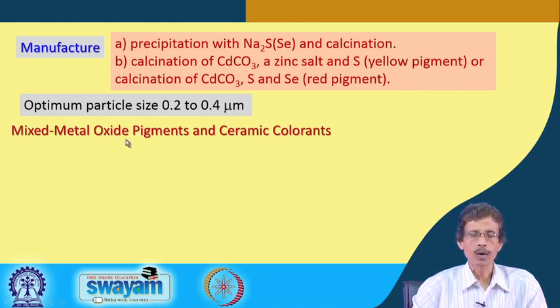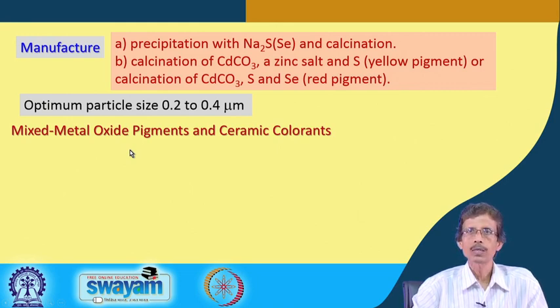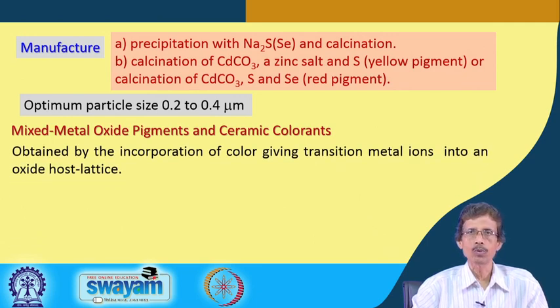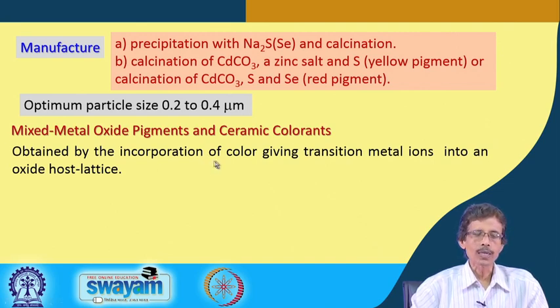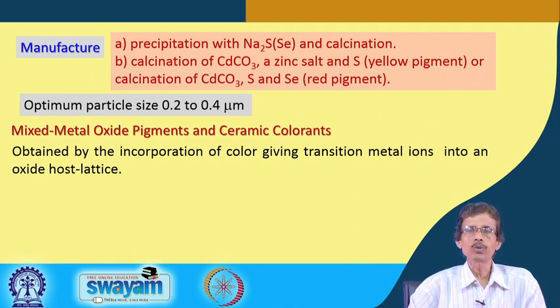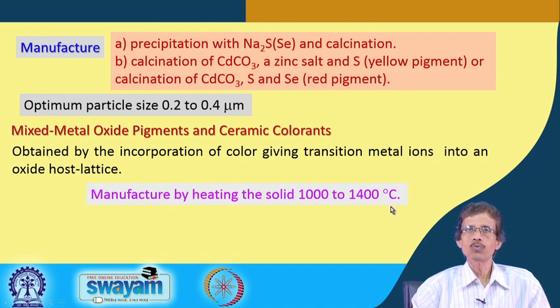Mixed metal oxide pigments are useful for ceramic applications. These are spinels — mixed oxides with high thermal stability compared to individual oxides. Colored transition metal ions are incorporated into colorless oxide host lattices such as alumina or magnesium oxide. The resulting material can be heated at 1000 to 1400 degrees centigrade.